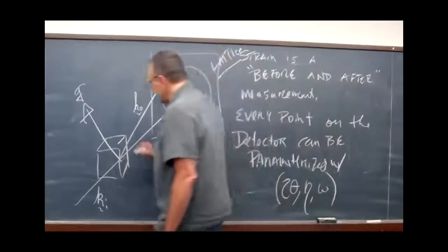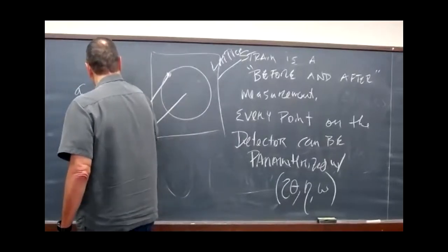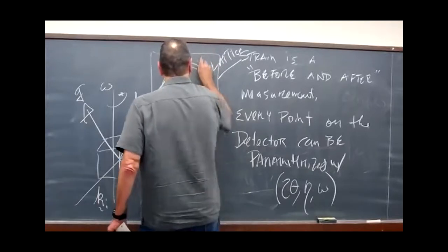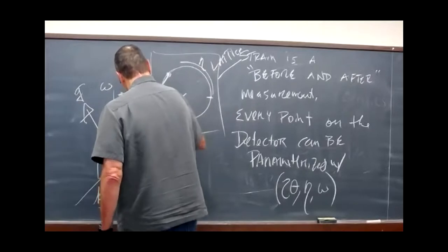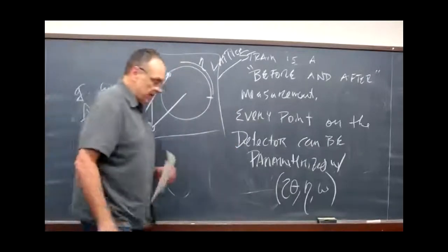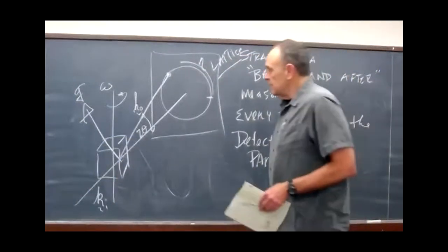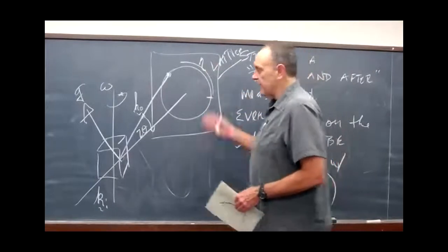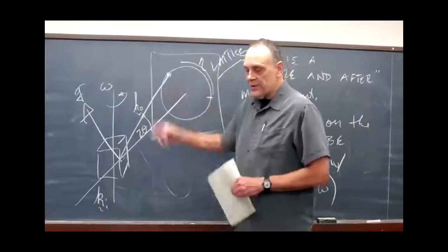Remember, in the rotating crystal experiment, we rotate about a vertical axis, omega. Our azimuthal direction is eta, and 2 theta is the Bragg angle. So you can parameterize, and Darren has often had the detector just with an XY coordinate system, and you convert the XY to these kind of polar coordinates.